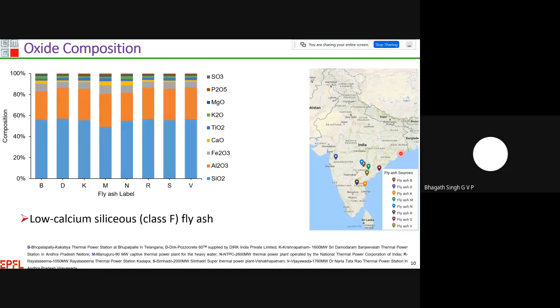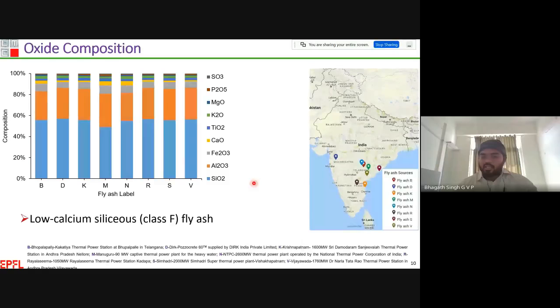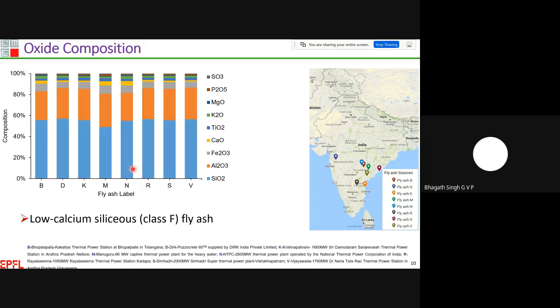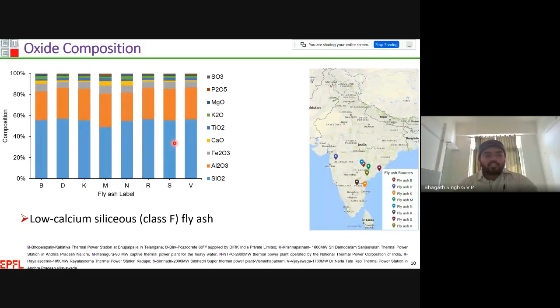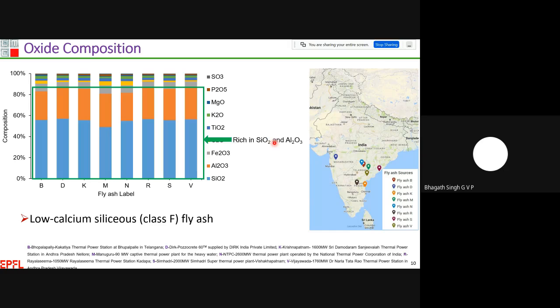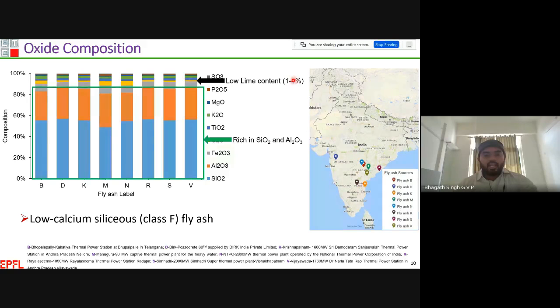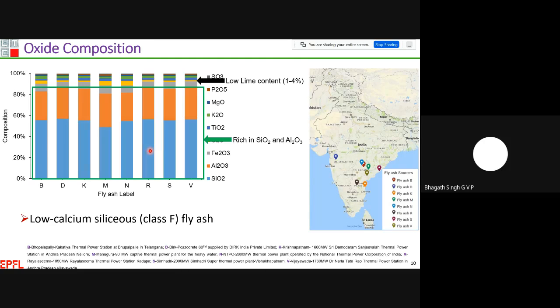Coming to the characterization, to know the importance of fly ash characterization, I have collected fly ash samples from various locations. These are the source locations I have mentioned here. Once I received the fly ash from these sources, I determined the oxide composition of all these fly ash samples, and the obtained values I have mentioned here. As you can see, all these fly ashes predominantly contain silica as well as alumina, about 75 to 85% silica and alumina content in most of these fly ashes, and being rich in silica and alumina, we see a very low lime content. The calcium content varies from 1 to 4% in all these fly ashes, along with other oxide compositions.